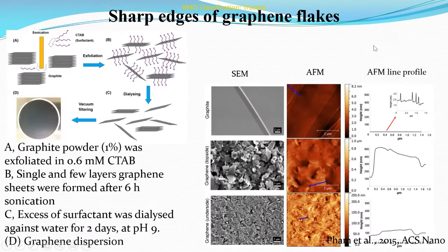Nanoengineered surfaces exhibiting dense layers of sharp blade-like nanostructures with 10 to 15 nanometer edges display very high rates of bactericidal activity. The randomly oriented knife-like nanosheets, which cover the surface in dense, exposed sharp edges, are distinctly different to the nanopillar topography. Therefore, the death of bacterial cells interacting with sharp nano-edges can be categorized as a distinct class of the mechanobactericidal effect of nanostructured materials. Here is an example of the bactericidal behavior of pristine graphene nanosheets — cell viability analysis indicated that up to 87.6% of Pseudomonas aeruginosa and 43% of Staphylococcus aureus cells were dead on these surfaces.